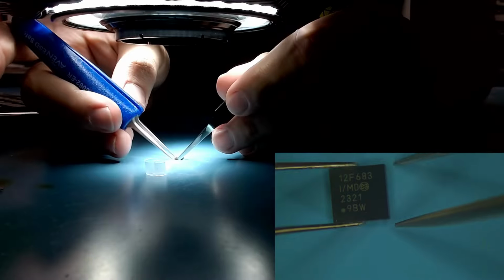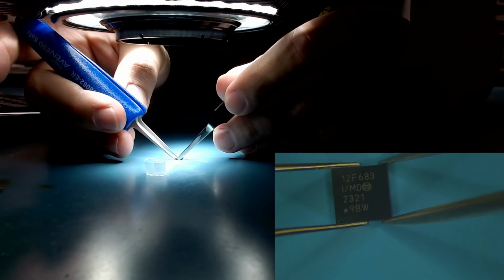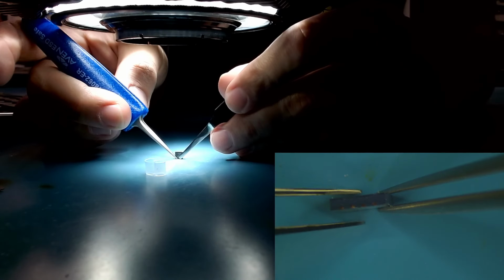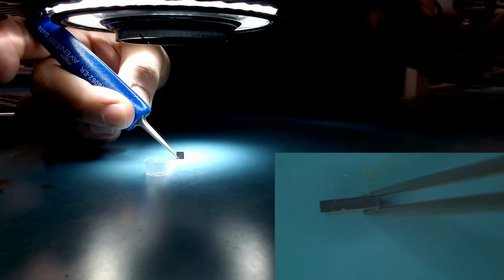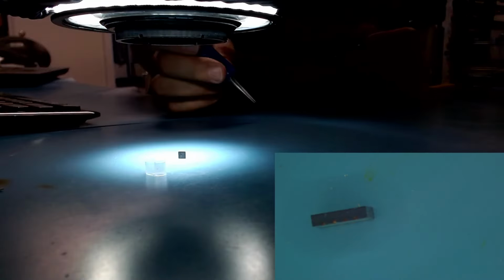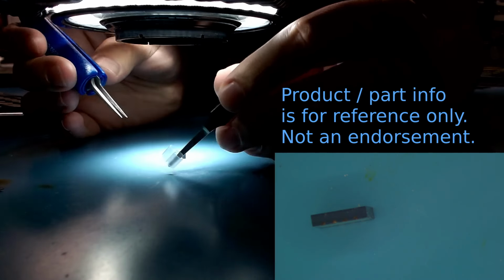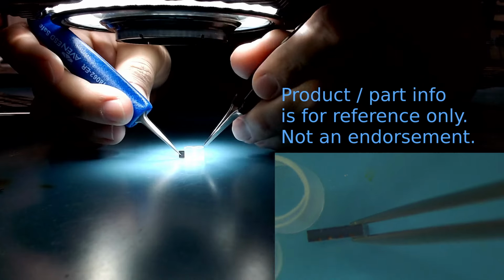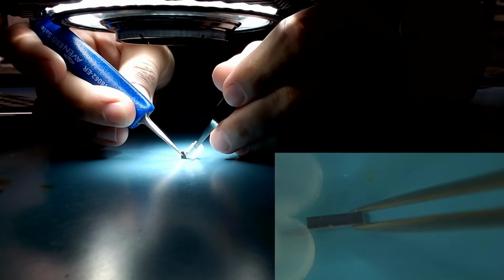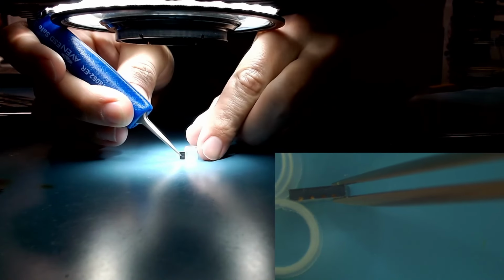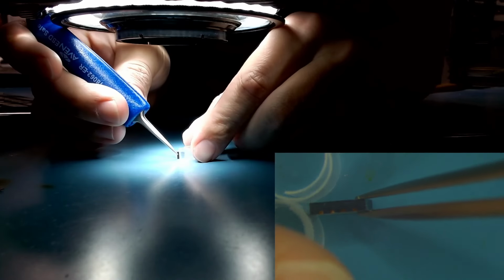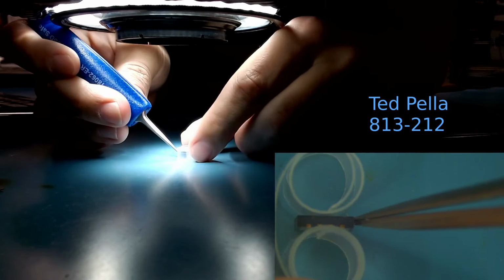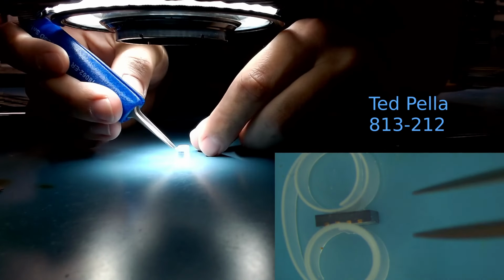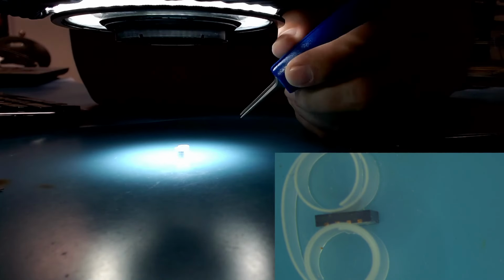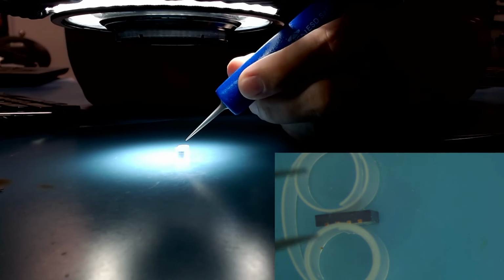And so the sample is going to get mounted edge on in this little plastic clip for cross-sectioning, and we're trying to polish in through 4 of the pins and ideally get all of the wire bonds in cross-section so that we can look at the package construction as well as the metal layer stack-up of the device and better understand how it's put together. And this is going to then be embedded in an acrylic resin for cross-sectioning.